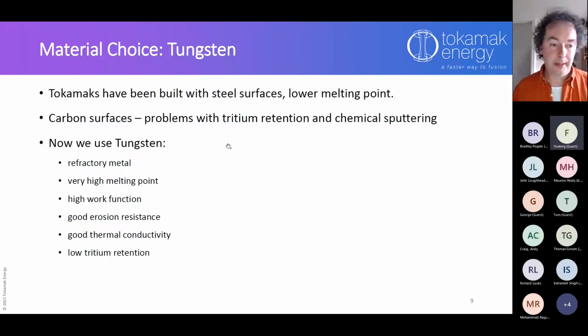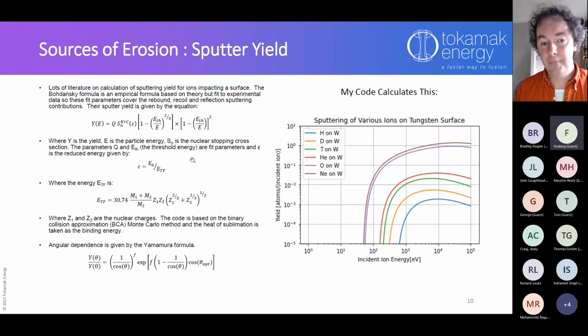So we use tungsten. It's a refractory metal with a very high melting point, work function, good erosion resistance, good thermal conductivity, and very low tritium retention. Molybdenum's another one, or other refractory metals might do the trick, but tungsten seems to be the best. Tungsten has the highest melting point of any metal we have. So we've been using tungsten, and here is a bunch of equations. I'm not going to go through them, thank goodness. This is to show that in the literature, sputtering has been looked at before by people much cleverer than me, and there's a variety of equations.